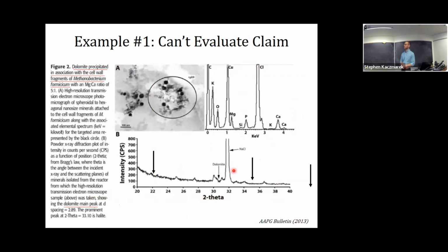Here's a study from 2013. You can see the claim in the figure caption: dolomite precipitated in association with the cell wall of the methanogenic bacterium, and they say the dolomite main peak is in the right spot. So here's the data—they say here's the main dolomite peak, that's that really tall 104 position. They have some images here, and some elemental data showing that this stuff does have magnesium and calcium in there. But this is their X-ray diffraction data, right?